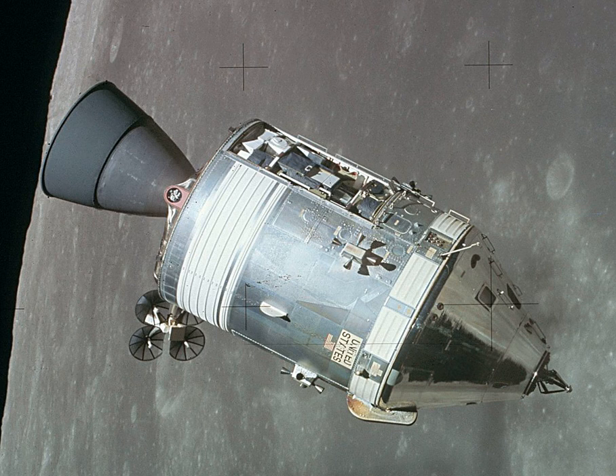It can also be found in electrolytic capacitors and in the most practical superconducting alloys. Niobium can be found in aircraft gas turbines, vacuum tubes and nuclear reactors. An alloy used for liquid rocket thruster nozzles, such as in the main engine of the Apollo lunar modules, is C103, which consists of 89% niobium, 10% hafnium and 1% titanium. Another niobium alloy was used for the nozzle of the Apollo service module. As niobium is oxidized at temperatures above 400 degrees Celsius, a protective coating is necessary for these applications to prevent the alloy from becoming brittle.